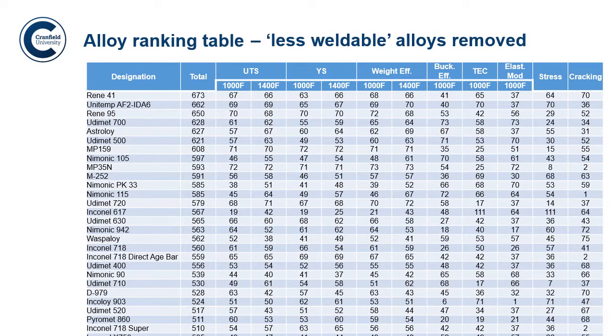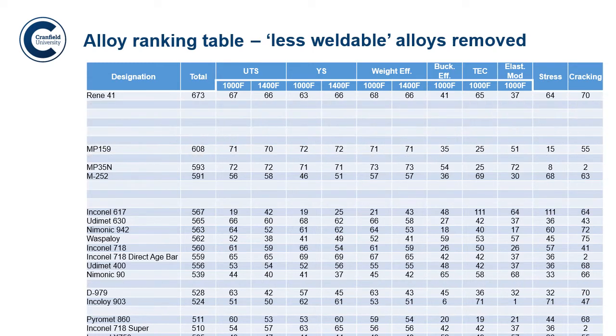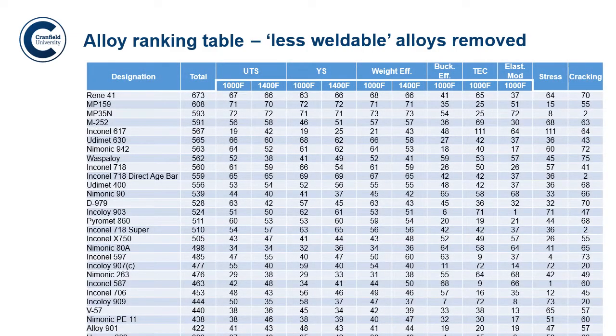So here's the alloy ranking table again. Now we're going to remove the less weldable alloys. That was all of the alloys that were significantly above the cracking line. We're going to get rid of those, and then we come up with this table. Again, Rene 41 comes out quite good because it wasn't significantly over the line. And then we have 718, which has moved up quite a bit in the table now, which is looking quite good, kind of more of a middle ground. But we still have the cobalt based alloy, Haynes 188, which is off the table still at the moment.